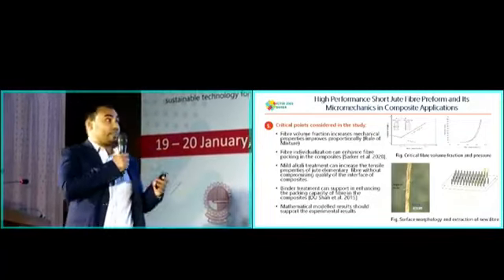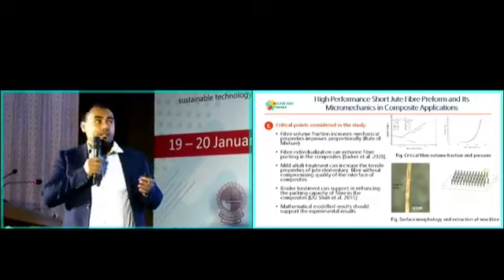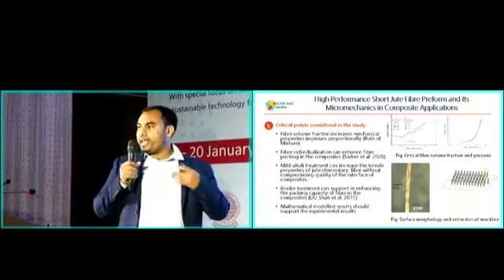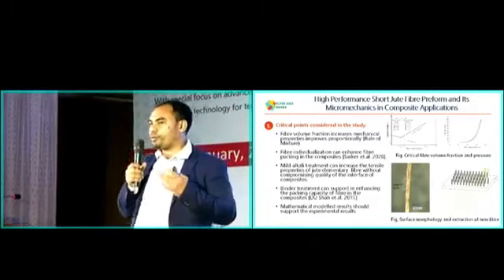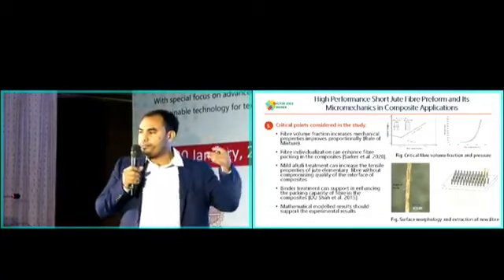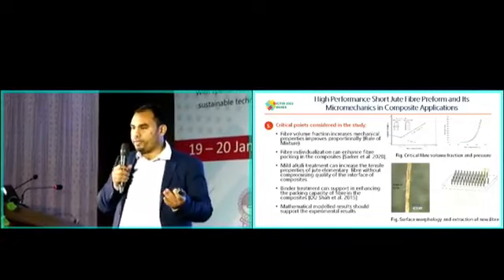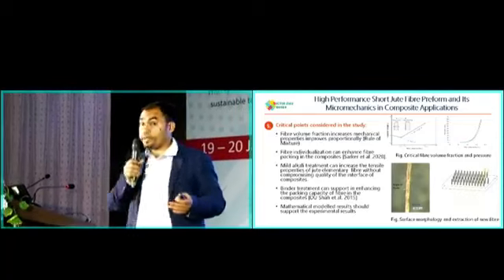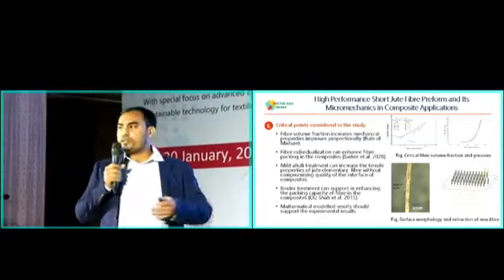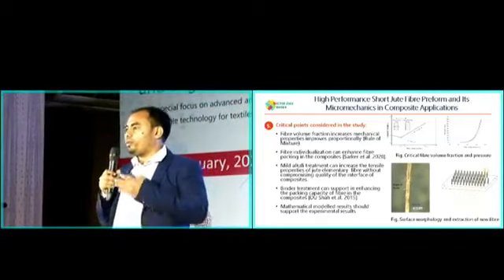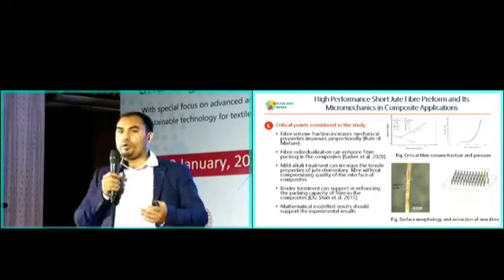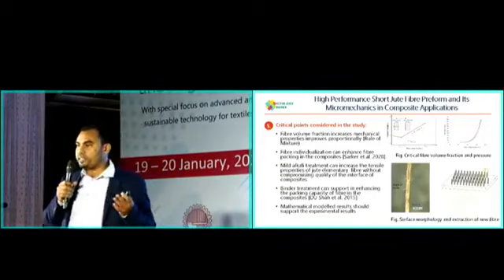So we have studied what is happening with this phenomenon. That means if the fiber content is much lower, then it is dominated by the matrix. If the fiber content is higher, then it is dominated by the fiber. That was already spoken about by the honorable keynote speaker. So we are trying to get the maximum mechanical properties by optimizing the maximum pressure, and there are also some other associated things that are considered in this study.